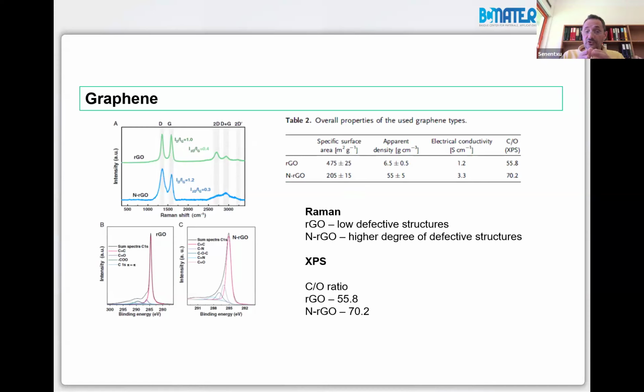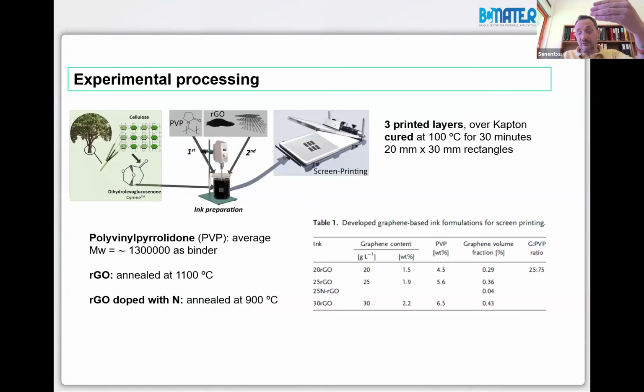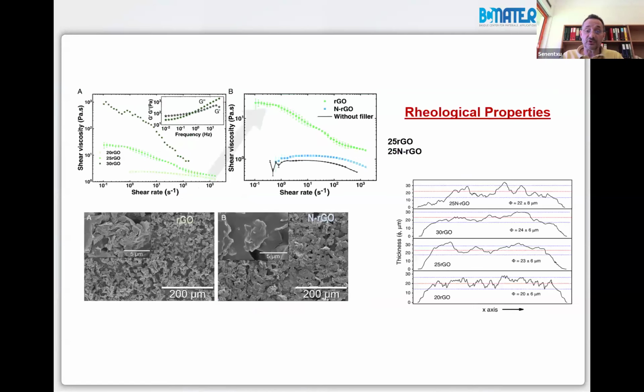By evaluating the graphene, also, the reduced graphene oxide has almost no defects, therefore the larger conductivity, but the other one, nitrogen-modified graphene oxide, has a higher level of defective structures. This is important because even for the same concentrations, we prepare different concentrations of the materials to tune properly the viscosity. You see a huge variation in viscosity depending on the concentration, which is normal, but for the same concentration, there is a clear difference in viscosity, an order of magnitude, depending on the fillers and the defects on the surface that I have used. That means that I can tune through concentration, but also affecting, obviously, the electrical conductivity of the material, or by the filler for the same concentration, not so much affecting the functional performance of the materials, but the printability that I am going to use.